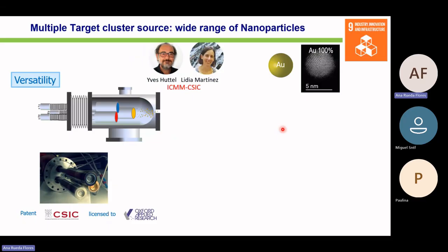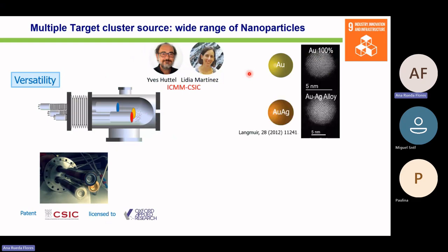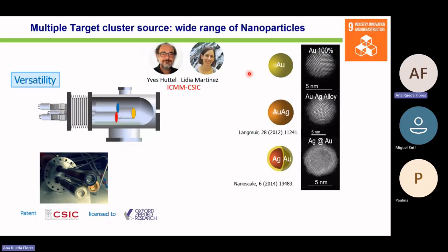Single element nanoparticles, when only one of the targets is switched on. Then if we put two of the targets at the same distance from the pinhole and we switch on both of them, we can have alloy nanoparticles. But then we can retract one of them, so we increase the distance to the pinhole. So first, we have clusters of the red material, let's say, and when they go in front of the yellow material, they are coated, forming a core shell nanoparticle, in which the core is red and the shell is yellow in this scheme. But we can do the other way around.